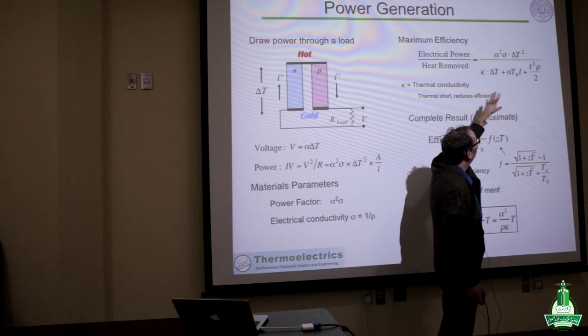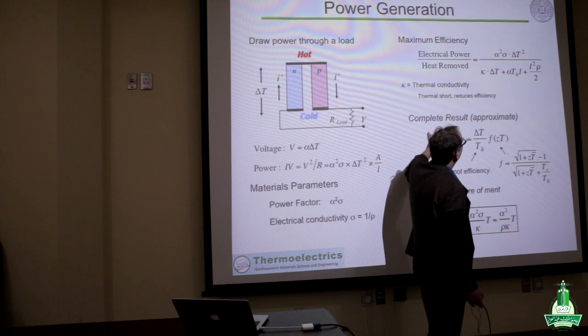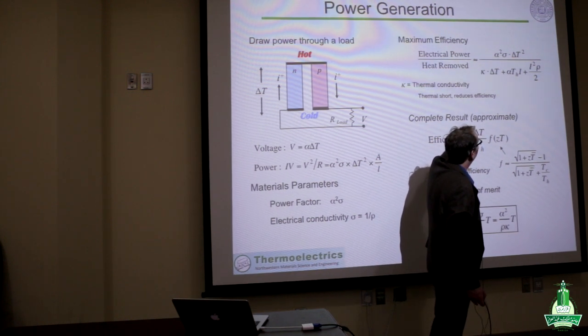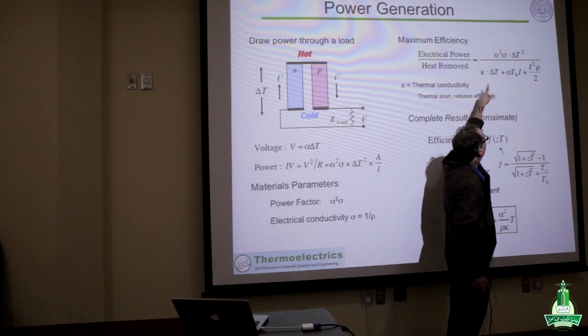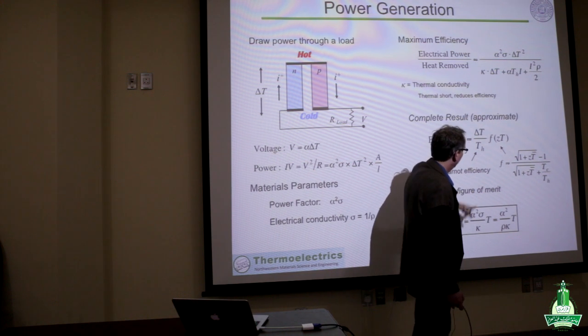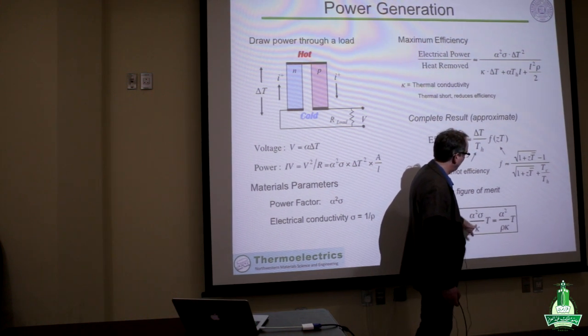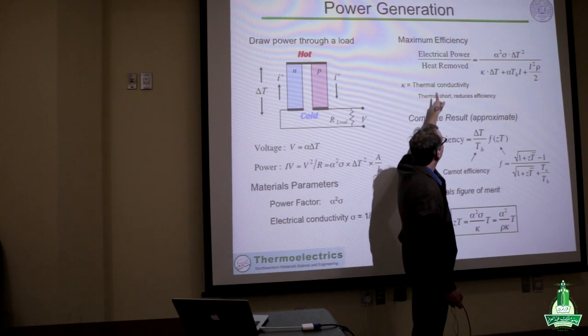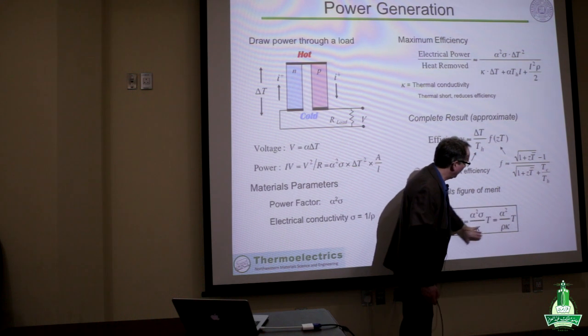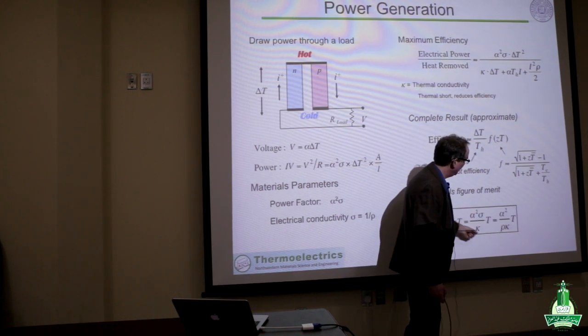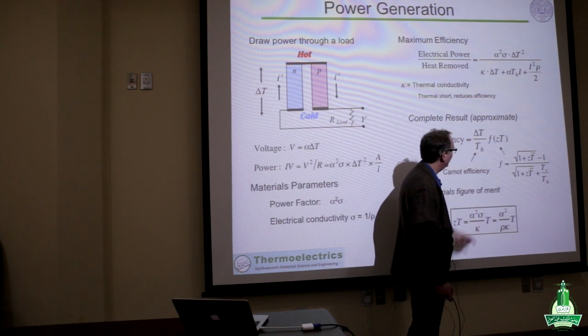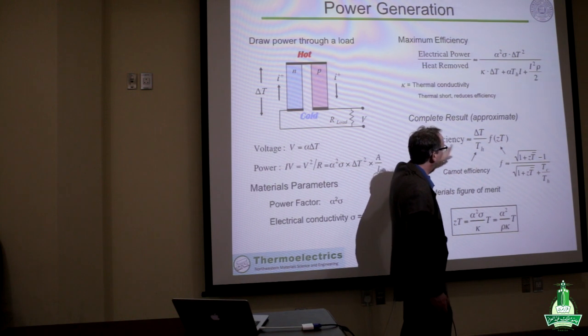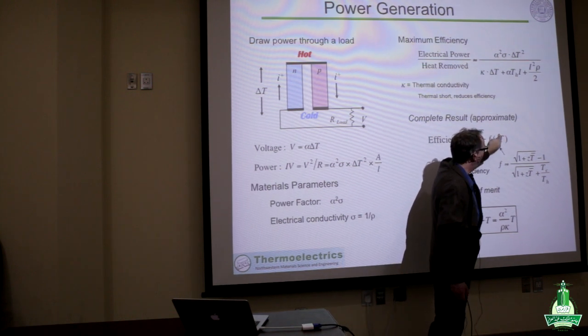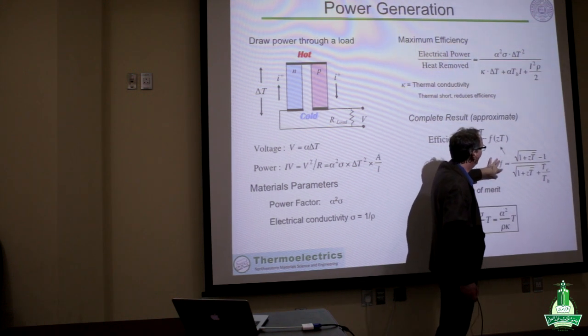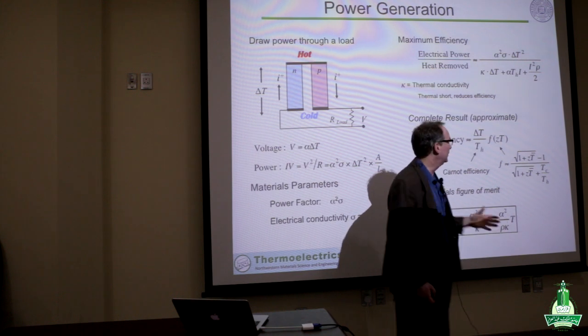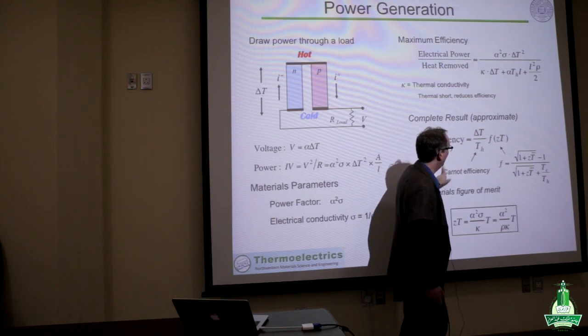Well, from this equation we can already see that the efficiency will have terms that include delta T and temperature, but also for the materials parameter, it will have this Seebeck coefficient squared times electrical conductivity over thermal conductivity by adding in the heat removed term. And so our materials figure of merit will be determined by these three factors. And then when we do calculate the complete result, we will see that this ZT parameter, the figure of merit, goes into a function which tells us our reduced efficiency, how much efficiency we get relative to our Carnot efficiency.